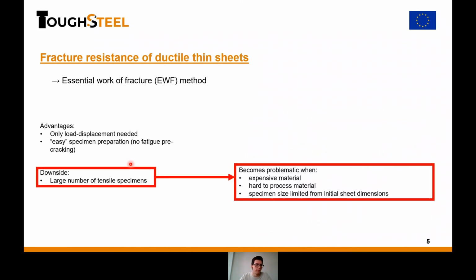This is typically fine in industrial settings where you have a large quantity of material, but it can become a bit problematic when you are working with expensive or hard to process material, or if your specimen size is limited by the initial sheet dimension. In my case, I worked with material that we would process in the lab, so I was limited both in size and in the total quantity of material. It was mandatory for me to find a way to reduce the total amount of material needed to perform the overall analysis.